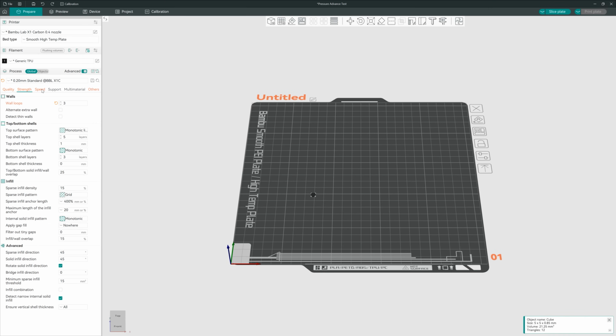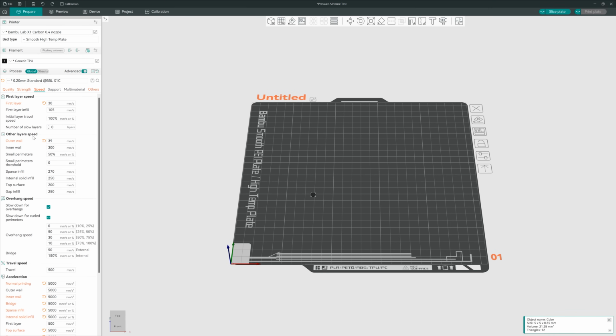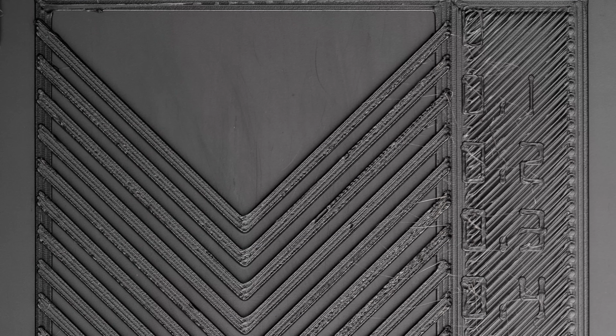We don't actually need to repeat the pressure advance test since, as we remember, the PA pattern method already reduced the print speed automatically to 30 mm per second. Still, out of curiosity, I ran the PA pattern test again, this time manually lowering the print speed to 10 mm per second. The results are as expected. All lines looked perfect, even with a K factor of 0, showing no signs of overextrusion in the corner. This makes sense. At such a low overall print speed, there's minimal acceleration or deceleration, so pressure advance has little effect. If we were to push the maximum print speed, pressure advance would naturally have an increasingly significant impact in compensating for extrusion lag and maintaining clean, precise corners.